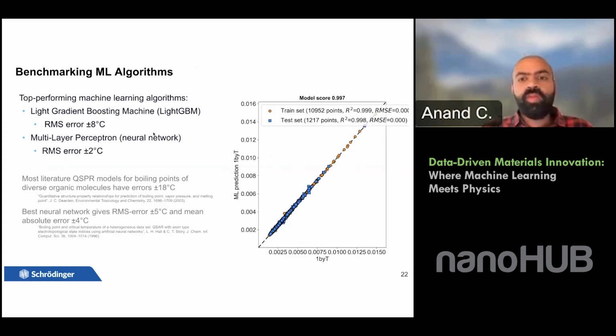So we trained a model for this data set of more than 12K experimental data points. The highest performing machine learning model was the multi-layer perceptron, which resulted in a root mean square error of around plus or minus 2 degrees Celsius for the boiling point of these organic molecules. The light gradient boosting machine did not perform as well. It was around plus or minus 8 degrees Celsius. And to our knowledge, this is one of the most comprehensive models of boiling points at different pressures for such a huge chemical space that's available out there in literature.